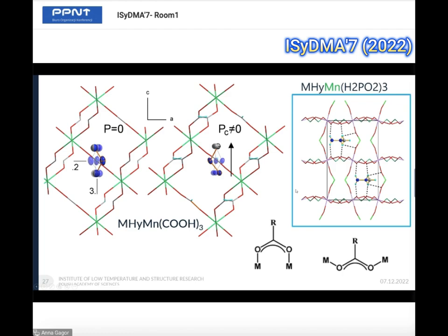So just to compare with formate, you can see that in formate we have a massively disordered cation, and in hypophosphite the inorganic part can very nicely adjust both to the size and to the number of the active NH groups for hydrogen bonding, and to produce a stable ordered crystal.